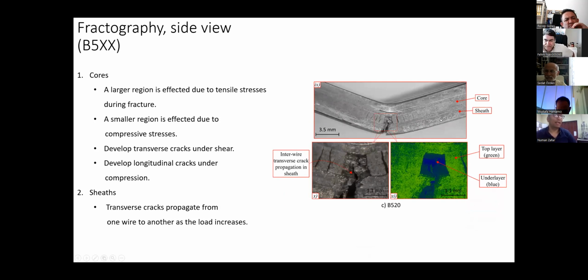This picture is prepared to show that the cracks which are produced in the wires, in the sheaths, are independent of the cracks which are produced in the cores. This image is prepared by an image analysis in which the bottom layer is painted in blue and the top layer is painted in green using the pixel information. Blue is the underlayer, and this crack, which was formed in another wire, this bottom wire, has propagated to the next wire. So if such a big transverse crack in the sheath occurs, the material fails before the core could do something. The load is reduced and the material fails because the cracks which are formed in the wires do propagate into the next wires.